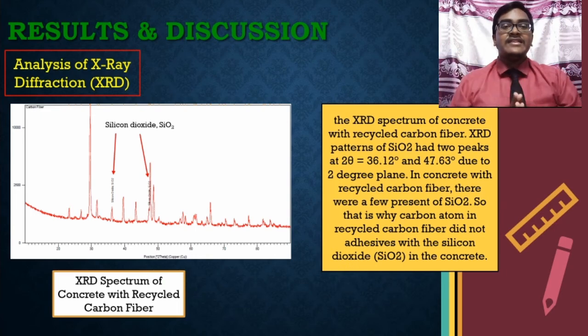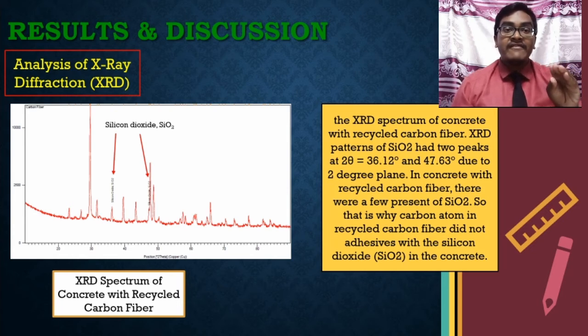Besides, the figure shows the XRD spectrum of concrete with recycled carbon fiber. The XRD patterns of silicon oxide had two peaks at 2 theta equal to 36.12 degrees and 47.63 degrees. In concrete with recycled carbon fiber, there was only a little silicon oxide, so the carbon atom in recycled carbon fiber did not adhere to the silicon dioxide in the concrete.